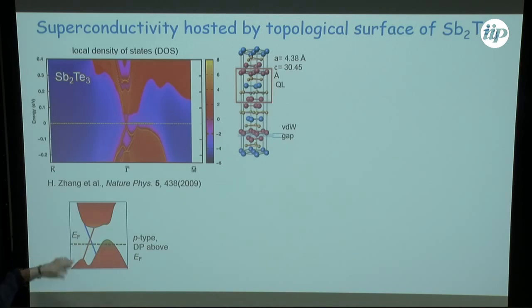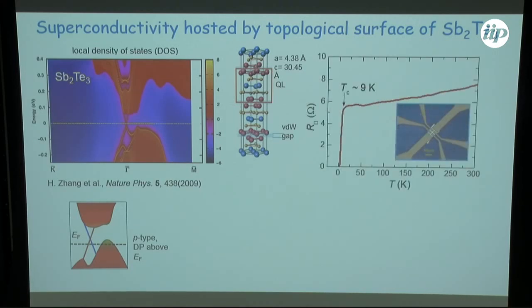Actually, the Fermi level in all bulk crystals of antimony telluride is p-type, so the Fermi level is usually very deep in the valence band, and the carrier densities are pretty high. I will show you that in our superconducting sample, the Fermi level is just below the Dirac point, and it cuts a little sliver of the valence band, which is our 2DEG, and that I will show you today.